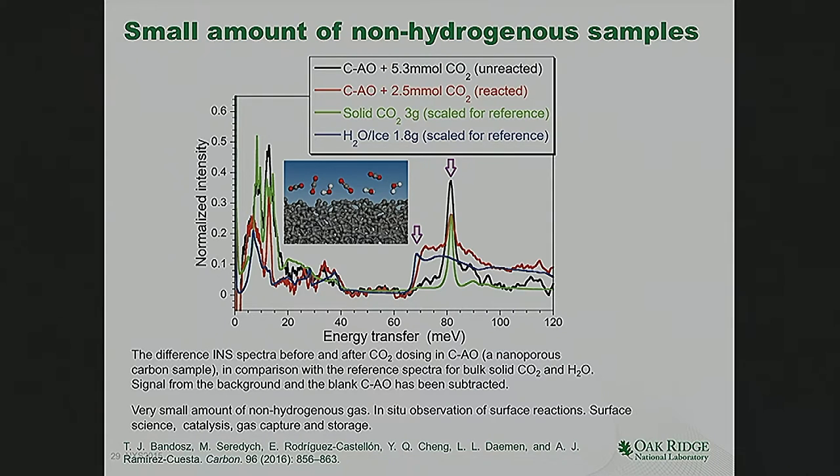And this is very important because the species that have been left in there are able to chemically react with CO2. And CO2 is really on the bottom of the thermodynamic well. So CO2 does not want to react in principle. But in this particular case, the catalyst is able to react hydrogen with CO2 and form water on the surface of the material. This is quite extraordinary, and the fact that you can measure this at all is absolutely, I mean, I would have called this science fiction 5 years ago.